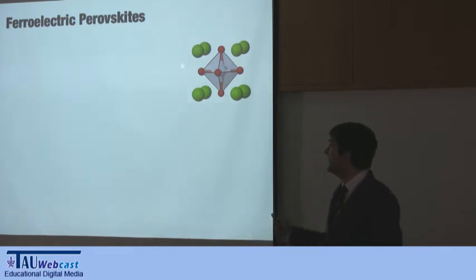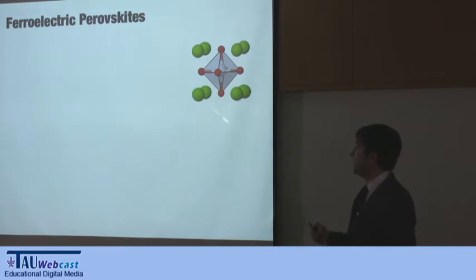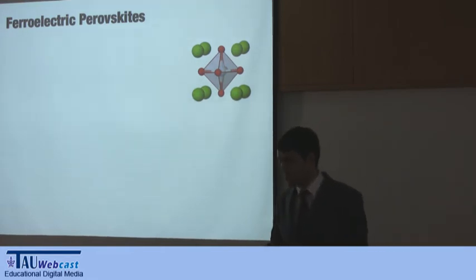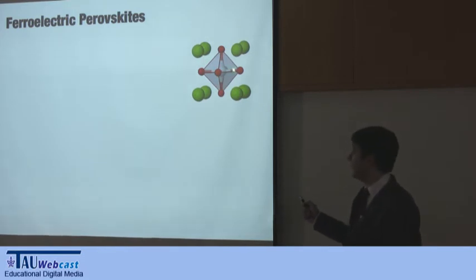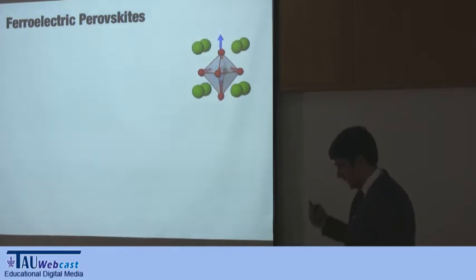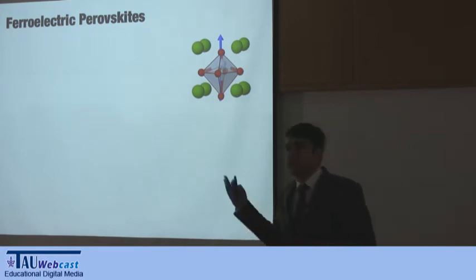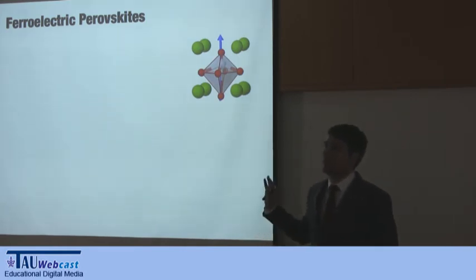So the ferroelectrics I've studied are all perovskites. Okay, this is a perovskite structure. For those of you that are not used to it, there are many materials that crystallize in this form. The chemical formula is ABO3. This is the B ion. Those are the A cations, and the B ion is surrounded by oxygens, 6 oxygens. So this is an oxygen octahedra, and most of the electronic properties come from the binding between the B cation and the oxygens. This is a perfectly cubic perovskite that exists only for a few of them.